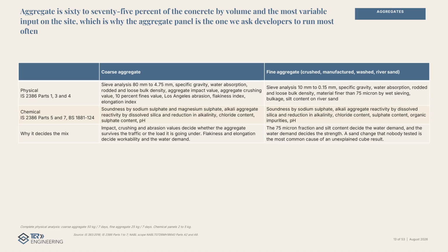Aggregate is 60 to 75% of the concrete by volume, and the most variable input on the site, which is why the aggregate panel is the one we ask developers to run most often. On the physical side, grading, specific gravity, water absorption, bulk density, impact, crushing, 10% fines, Los Angeles abrasion, flakiness and elongation. On the chemical side, soundness in sodium and magnesium sulfate, alkali aggregate reactivity, chloride, sulfate, and organic impurities.